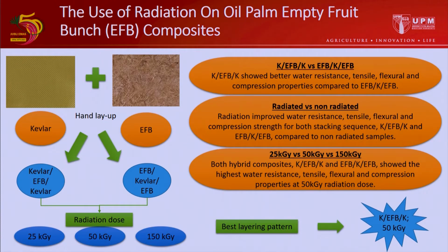At the end of this study, it was found that the hybrid composite, which uses EFB as its core and radiated at 50 kGy, has the best mechanical properties, which can be further analyzed for impact properties.